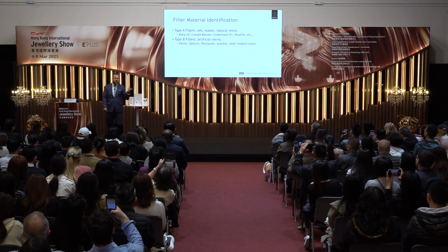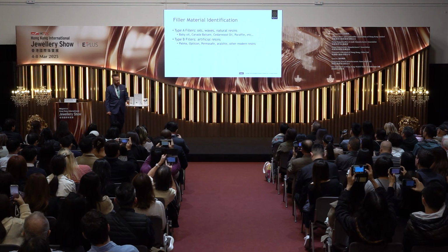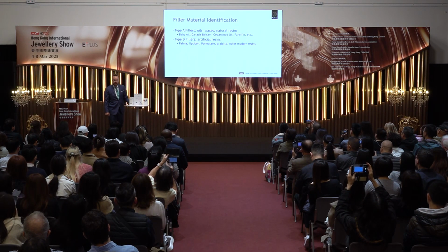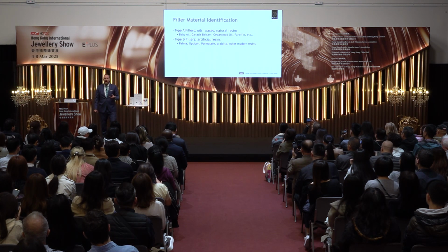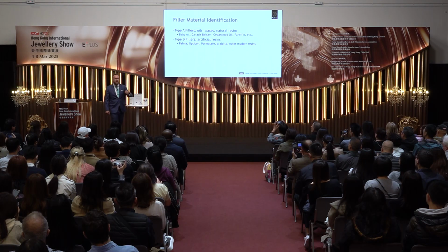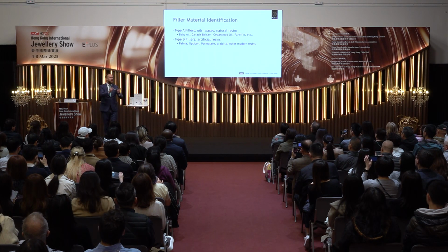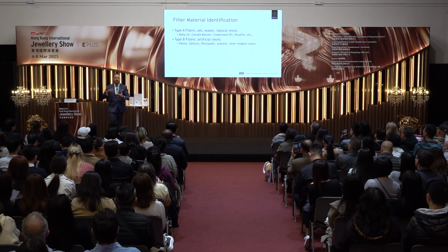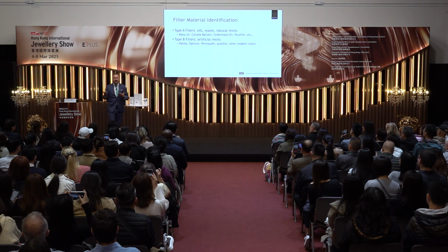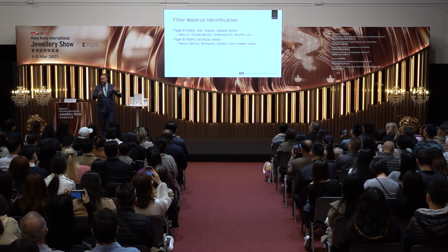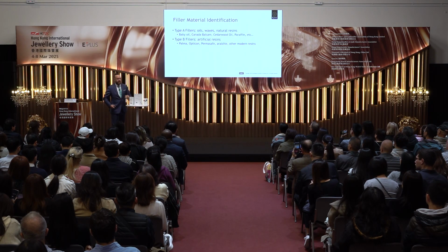Then we have the type B filler. So these are artificial resins, very often specifically designed industrial products for this purpose. So very often they do a very good job at clarity enhancing, and they tend to be a lot more stable. So things like Palma, Opticon, PermaSafe, which are sometimes two different products that are mixed together, where it is one product put in and then another product added to stabilize it using UV. These are artificial resins that we would classify as a type B filler.